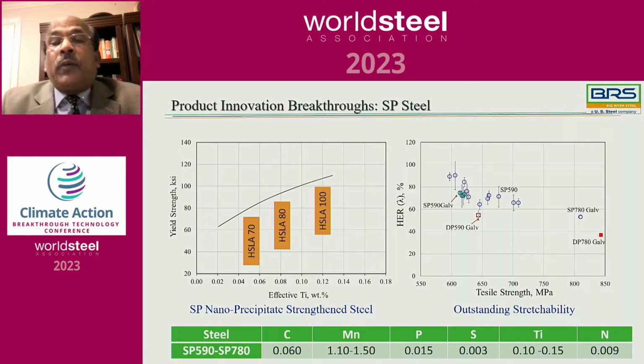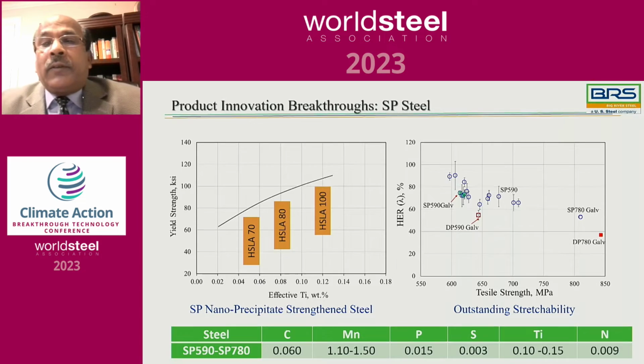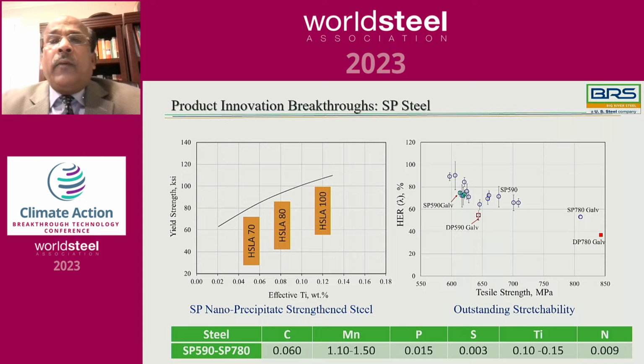On the right-hand side, it shows the hole expansion ratio obtained in this steel at different strength levels, compared with dual phase steel of similar strength. Across the whole spectrum of tensile strength levels, you can see outstanding hole expansion ratio, which exceeds that manifested by DP590 or DP780 steel. So this SP780 steel is a very apt substitute for DP780 steel.